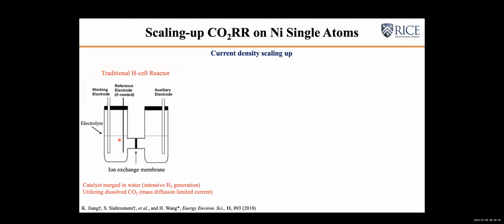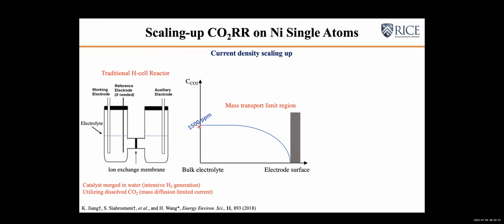So think about that. Surrounding your electrode surface area, less than 0.001% is CO2 molecules. Actually, 99.999% is water molecules. So in that case, of course, it's very easy for the HER to pick up. And also think about this mass diffusion limit. The bulk concentration of CO2 is only 1,000 to 2,000 ppm.